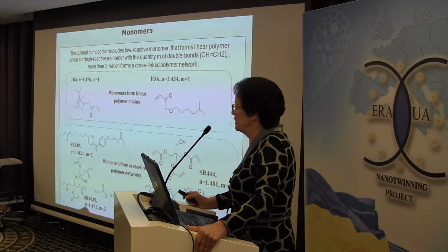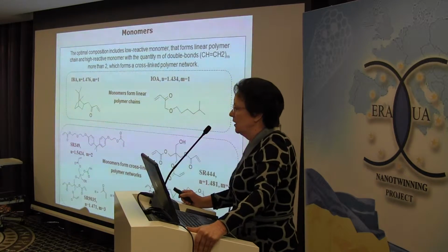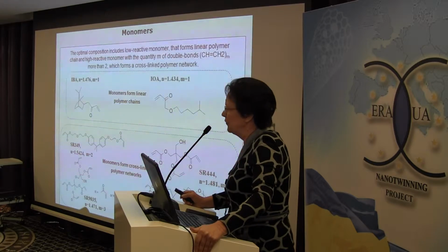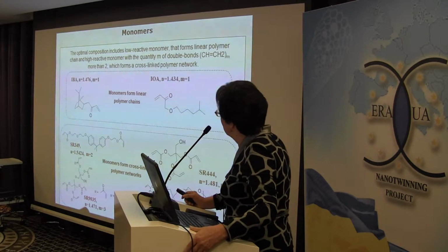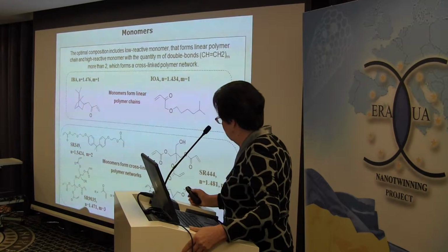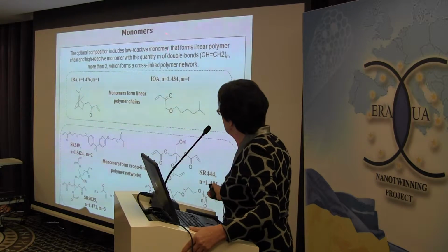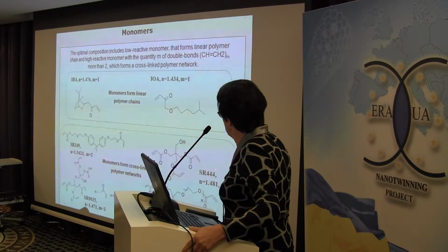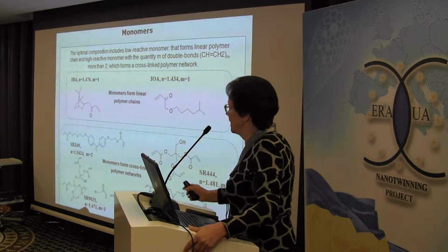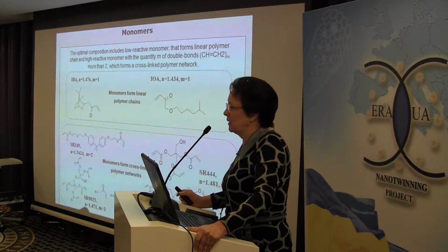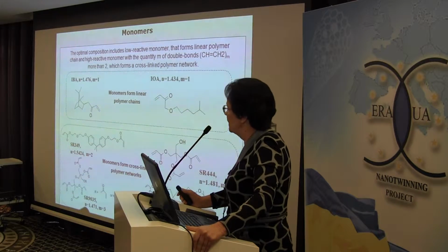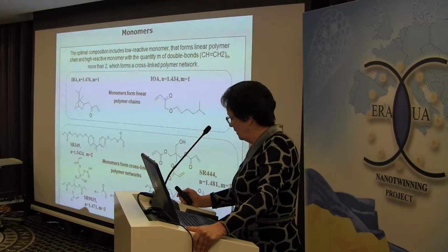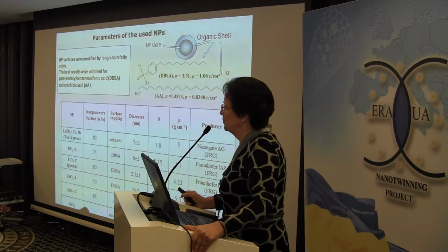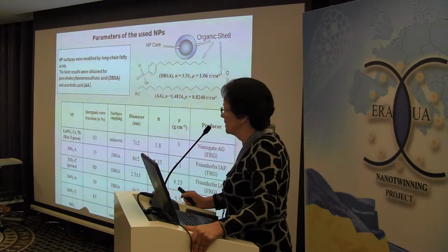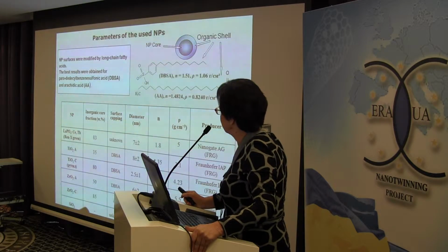It should be noted that all these compositions are suitable for holographic patterning, but the mixture of this monomer with one of the low reactive monomers gave us the best results. The properties of nanoparticles are shown in this table.